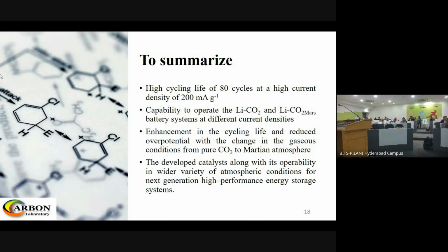So high cycling life till 80 cycles with the current density of 200 milliampere per gram. And we were able to use the system at different current densities, which is important for the different applications. And then, of course, there is an enhancement in the cycling life and reduced overpotential. And this developed catalyst also shows that it can be used in a variety of atmospheric conditions.